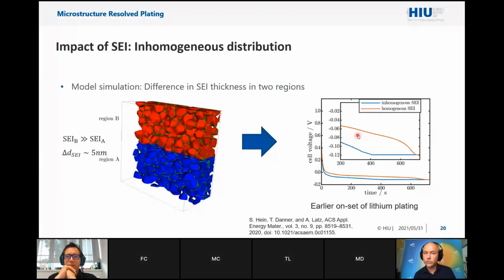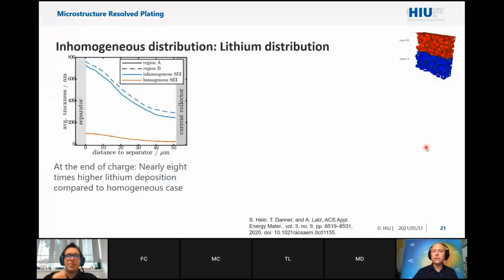You see that in the inhomogeneous situation, the drop in voltage is much bigger, so the amount of overpotential produced is much bigger than in the homogeneous one. It's not surprising that we get a bigger drop in the overpotential, since there is a part which has a larger interface resistance and the SEI is thicker. What is amazing is that the plating is going to happen much faster, since you reach the plateau regime in a very much shorter time than if you just stay in the homogeneous regime. And not only that, you also see that the amount of lithium produced is much bigger in the inhomogeneous simulation, which is this one, compared to the homogeneous one.